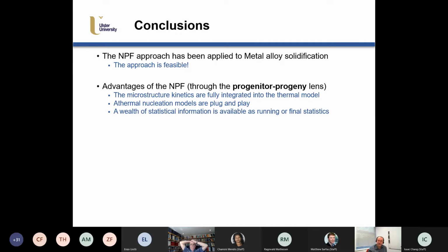The microstructure kinetics are fully integrated into the thermal model. Indeed, the microstructure nucleation and growth rates drive the latent heat. Athermal nucleation models are plug and play. So we can go back and put in any athermal description, whether it's a Greer log normal, or a delta Dirac, which would model explosive nucleation. We could use any kind really, and just look across and analyze it in different modes.